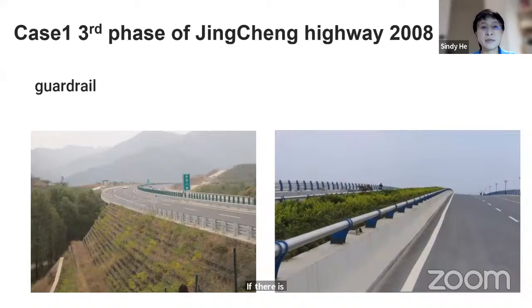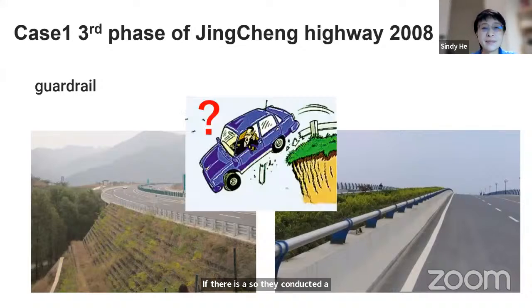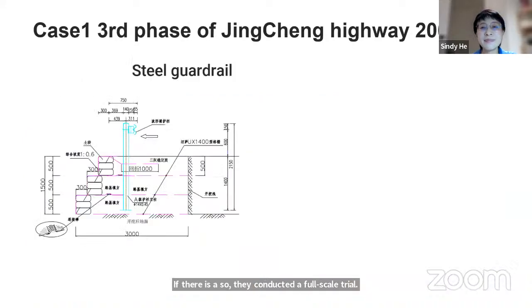So they conducted a full-scale trial. That is very interesting. They built a full-scale slope which is just 1.5 meters high. The face angle is also 60 degrees. It's the same as the real slope. The slope was reinforced by the UX1400 geogrid with 500 millimeters of spacing. The geogrids wrap around the backs and connect to the upper geogrids using the bodkin.